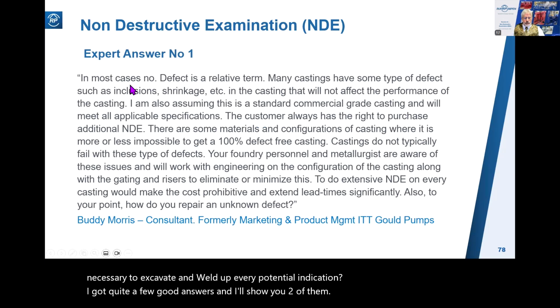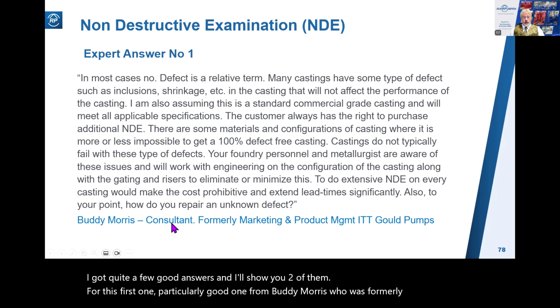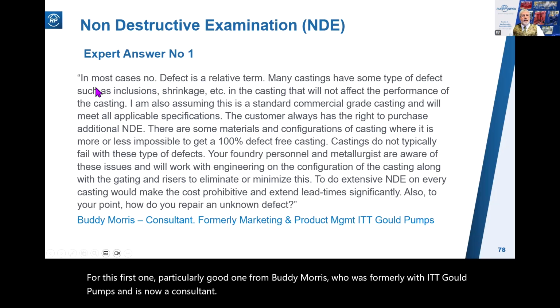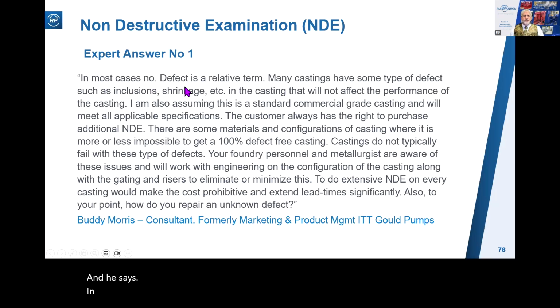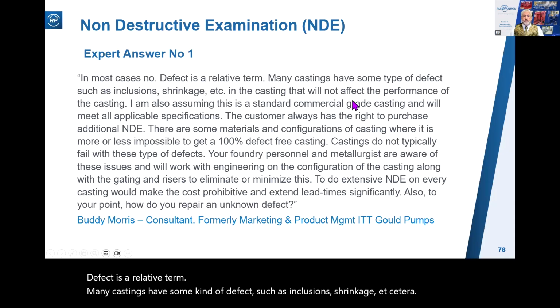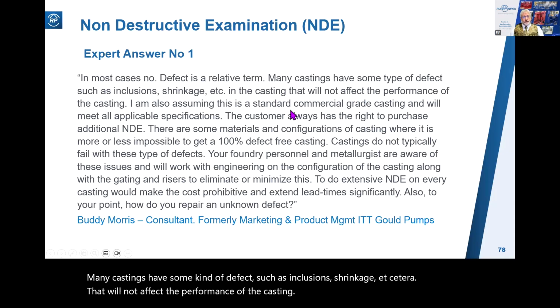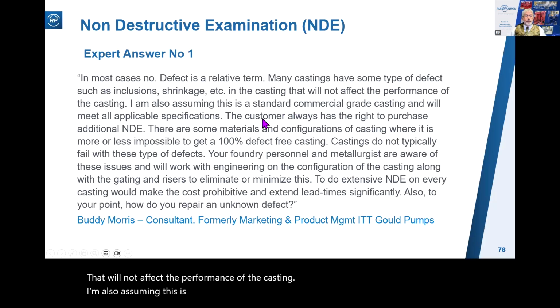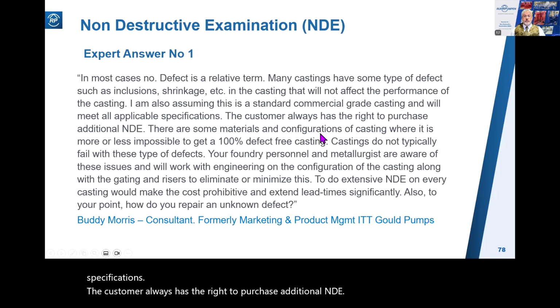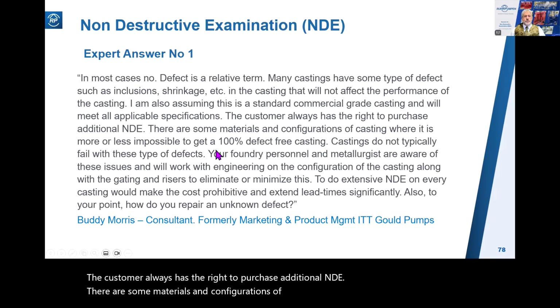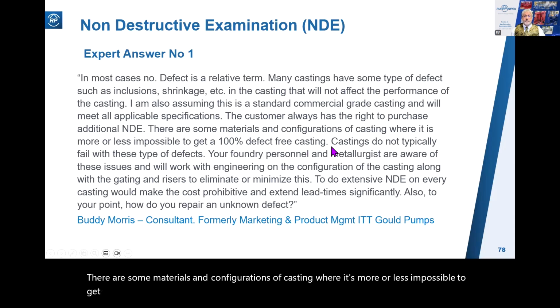This first one, a particularly good one from Buddy Morris, who was formerly with ITT Goulds Pumps and is now a consultant. And he says, in most cases, no. Defect is a relative term. Many castings have some kind of defect, such as inclusions, shrinkage, etc., that will not affect the performance of the casting. I'm also assuming this is a standard commercial grade casting and will meet all applicable specifications. The customer always has the right to purchase additional NDE. There are some materials and configurations of casting where it's more or less impossible to get 100% defect-free casting.